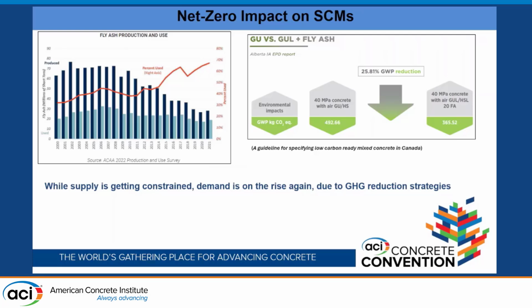So if you compare a 40 MPa concrete made with general use cement, you get a certain GHG over here. Now if you replace that straight cement with type 1L or GUL plus fly ash, you get an immediate reduction of global warming potential of up to 25%.